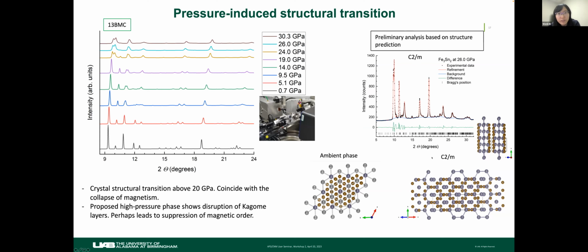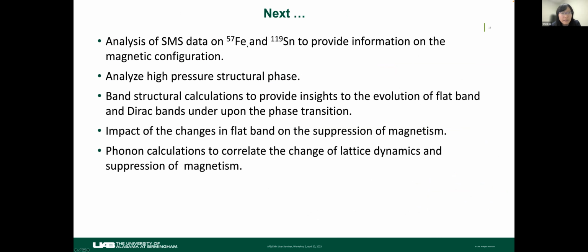This is a fit with the proposed C2/m based on the calculation, and the fit is reasonably good. If we look at the crystal lattice of this proposed structure, we concluded that if this is the real high pressure phase, the Kagome lattice is disrupted, and that could be the reason for the suppression of magnetic order. Okay, so next we're going to analyze the Mossbauer data on both iron and tin, to look at this exchange interaction. Hopefully we can provide some information on the magnetic configuration and the exchange interaction, and also look at this high pressure crystal structural phase more carefully.